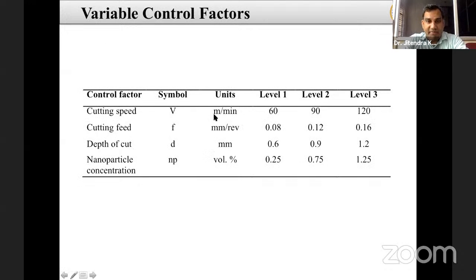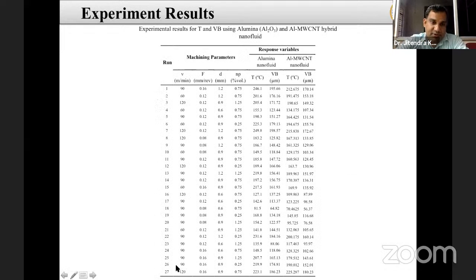So here also we take the cutting parameters, 3 levels, 4 parameters: velocity, feed, depth of cut, and nanoparticle concentration. So the same 0.25, 0.75, 1.25, and we increase the speed 60, 90, 120. So these are the 3 levels, and here I have used the RSM method, which is also an optimization method. In this RSM method, we designed 27 experiments, and we also measured the temperature at the interface by a K-type thermocouple, and we measured the flank wear in microns. So for alumina nanofluid, single nanofluid or hybrid nanofluid, we observed that particular data, and in that data we observed that 0.75 gives the lowest, 56 micron flank wear, rather than other cases.